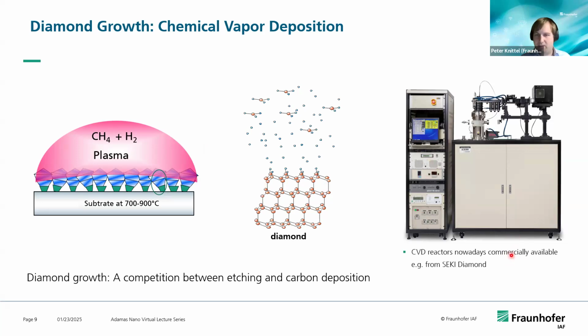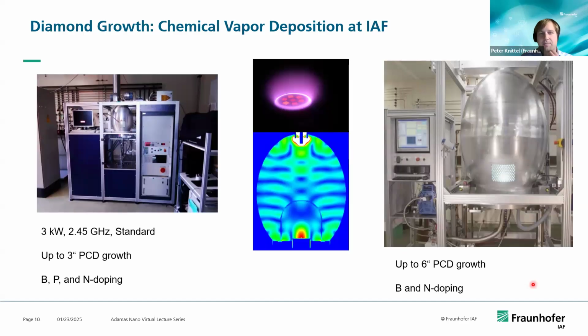Nowadays, you can get these nice reactors from Seki Diamond. We also have one of them, but in our institute, we actually designed our own machines that you can see here. They have a very typical shape. This is this ellipsoidal shape, which has the advantage that the microwave that we couple into the resonator is coupled in via an antenna on the top part in the first focal point of this ellipse, and it refocuses in the bottom part where we also locate our samples.